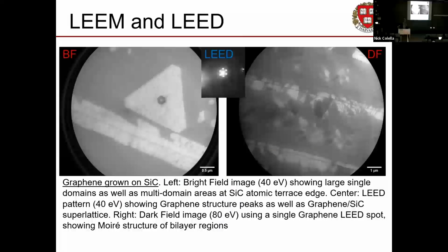Okay, here's some stuff we can see. Here is some graphene actually being grown in real time. You can see nice hexagon facets on it. That's a little triangle of graphene. It's nucleated at a point defect on a piece of silicon carbide. This particular sample got really hot because, as I mentioned, we can make things really hot in this tool, and it started to spontaneously grow graphene.